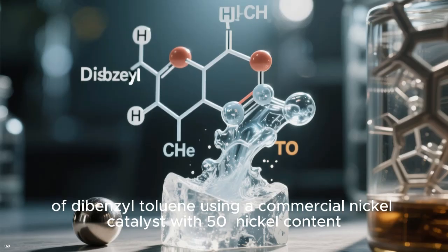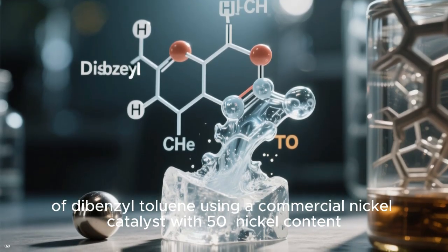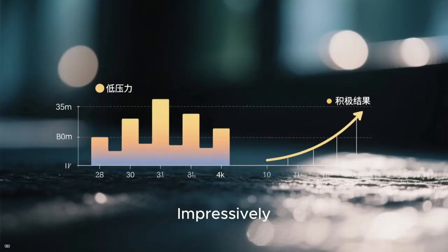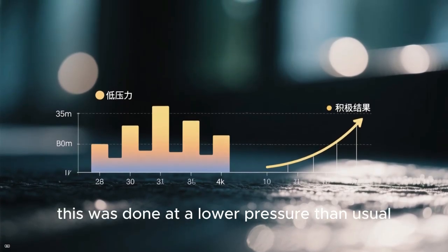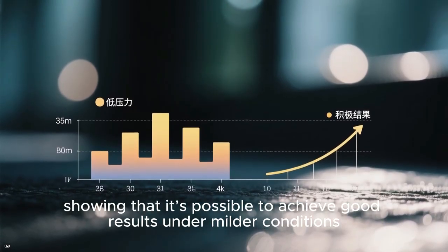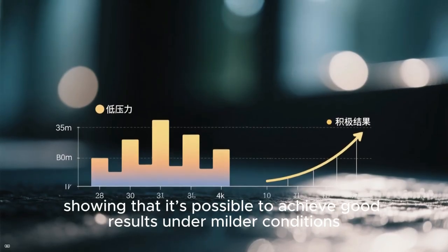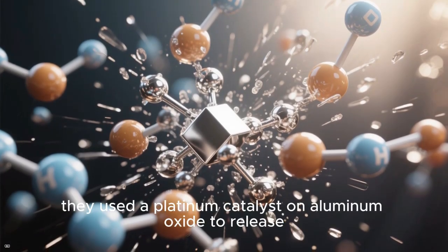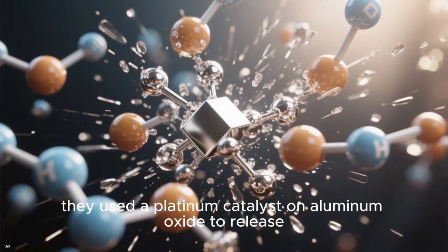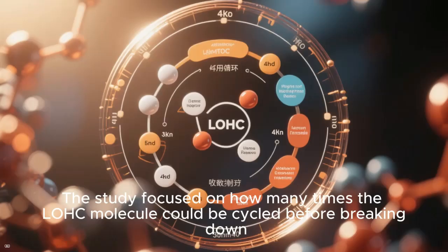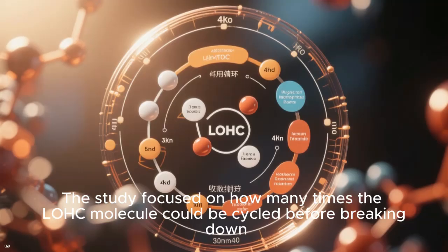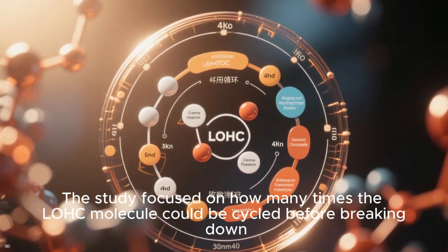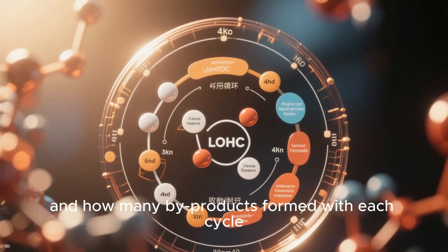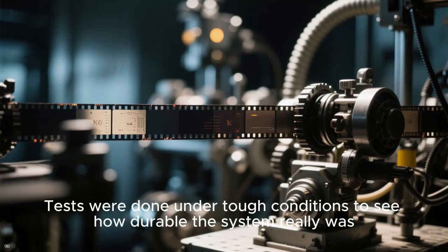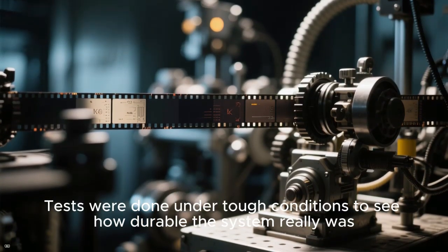To give an example, a study tested the complete hydrogenation of dibenzyl toluene using a commercial nickel catalyst with 50% nickel content. Impressively, this was done at a lower pressure than usual, showing that it's possible to achieve good results under milder conditions. For the dehydrogenation step, they used a platinum catalyst on aluminum oxide to release hydrogen from perhydrodibenzyltoluene. The study focused on how many times the LOHC molecule could be cycled before breaking down and how many byproducts formed with each cycle. Tests were done under tough conditions to see how durable the system really was.